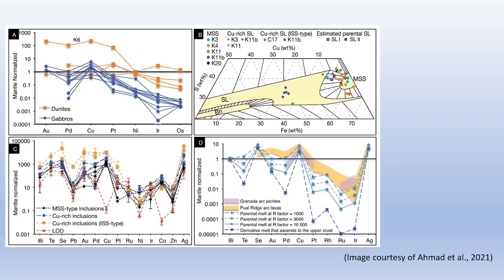And panel C is where it gets really striking. The copper-rich inclusions, especially the ISS types, are absolutely loaded with palladium, platinum, and gold, up to thousands of times mantle levels and values. This tells us that even tiny sulfide droplets are incredibly efficient at scavenging chalcophile and siderophile metals. In contrast, the MSS type inclusions lean toward nickel and cobalt, showing internal zoning and chemical evolution as the sulfide melt cooled. And this kind of high resolution fingerprint with PGEs so strongly partitioned is rarely preserved and offers a unique window into the deep magmatic filter.